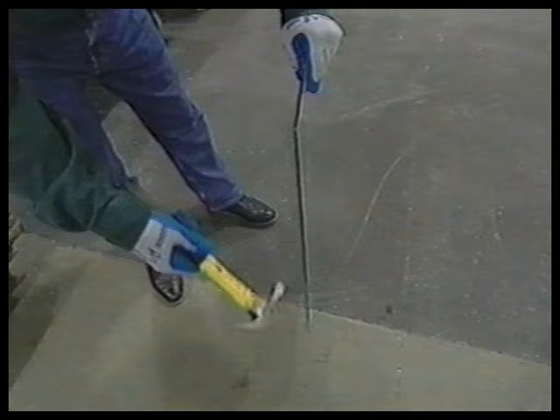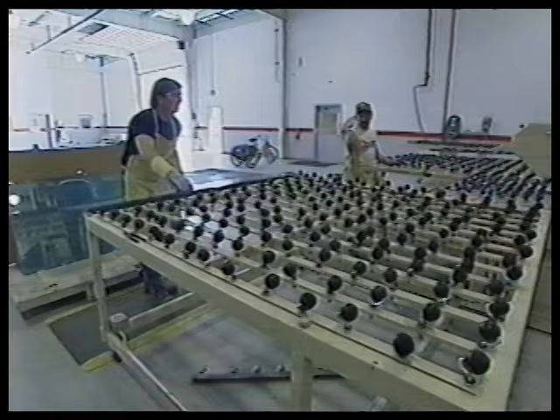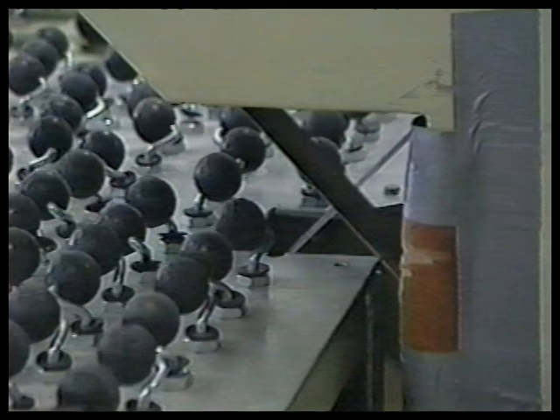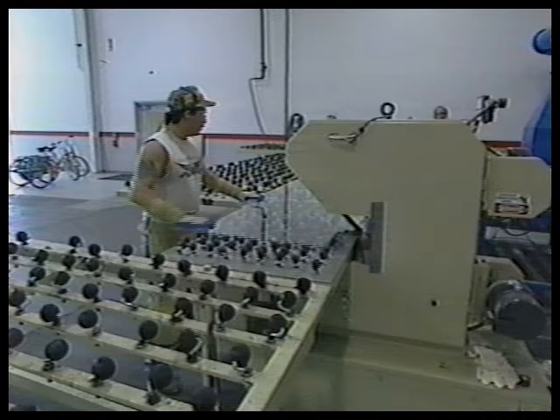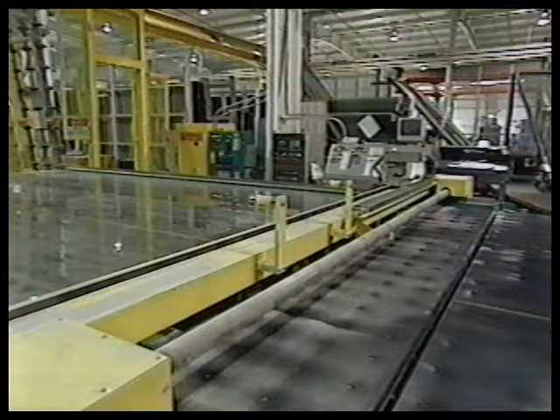Most architectural glass can be tempered. Once annealed glass has been fully tempered, it is not possible to alter the appearance of the piece. For instance, holes, polished edges, and notches must all be completed before the glass is tempered. If any additional processing is attempted after tempering, the piece will shatter.